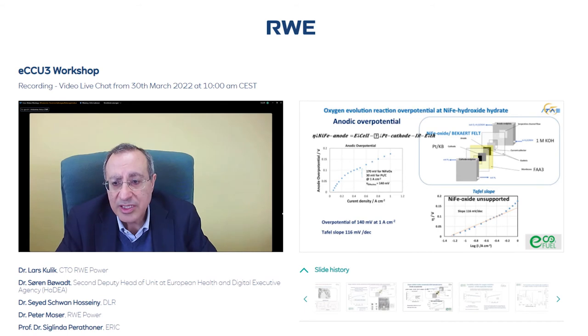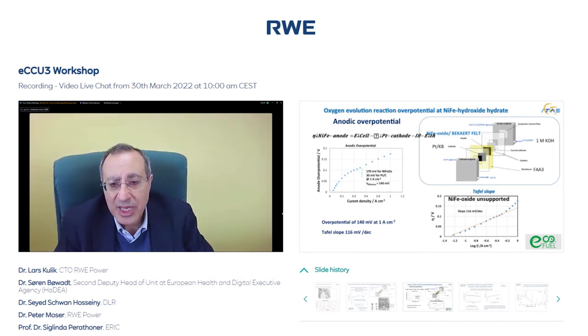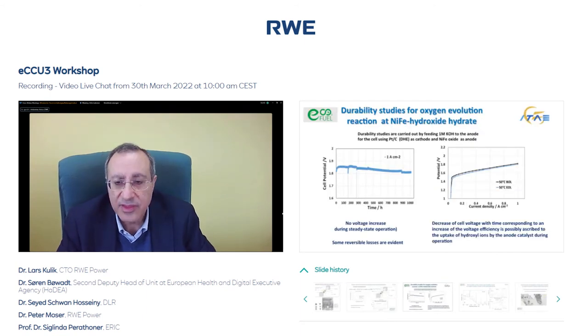Now, moving to slide number 10, we can get some more detailed information about the overpotential at the anode, using a reference electrode and after some correction for the ohmic drop and the thermoneutral potential. We can see that at 1 ampere per square centimeter, we have 140 millivolts of overpotential and a Tafel slope of 116 millivolts per decade, that is corresponding to one electron transfer process as a rate determining step for the oxygen evolution reaction. And it is pointed out that this is achieved at practical current densities.